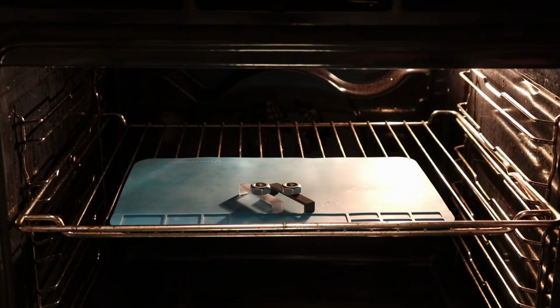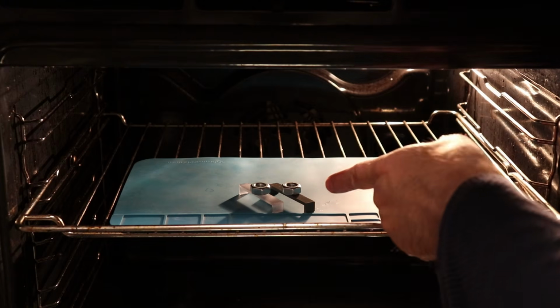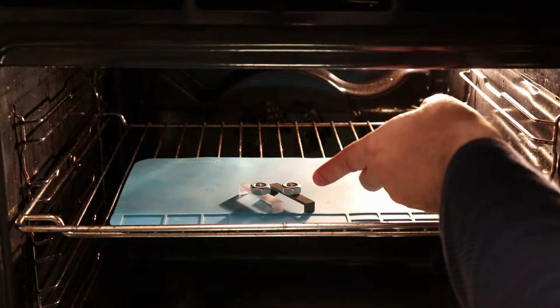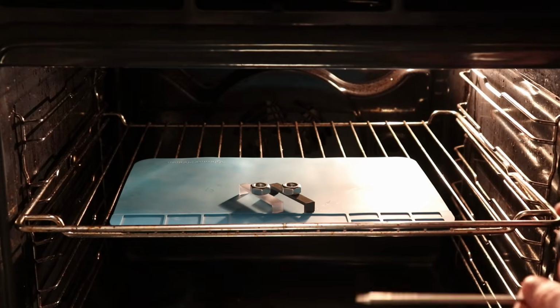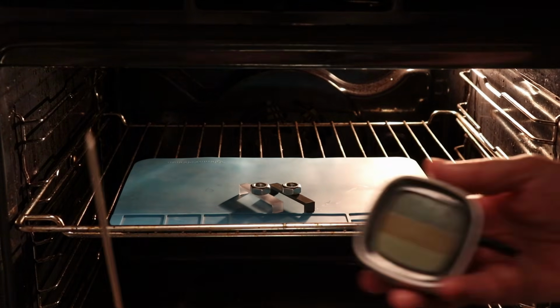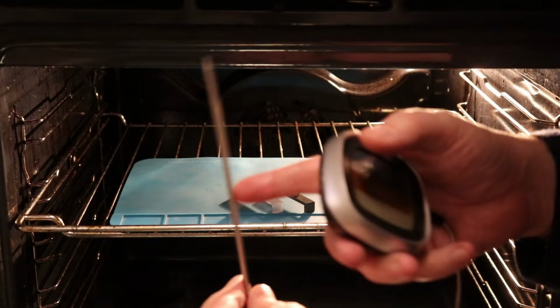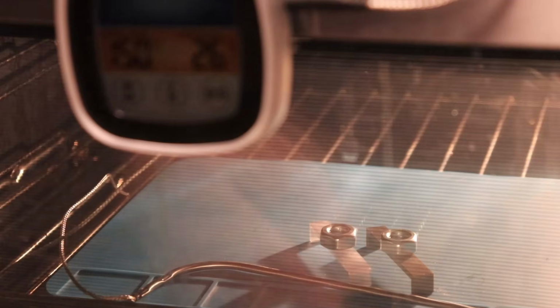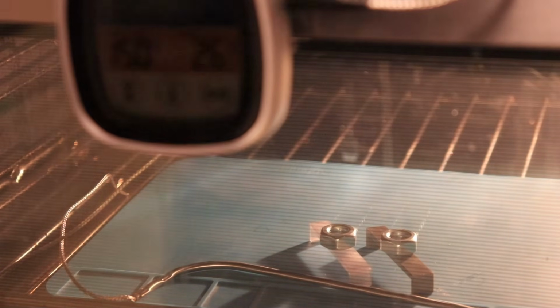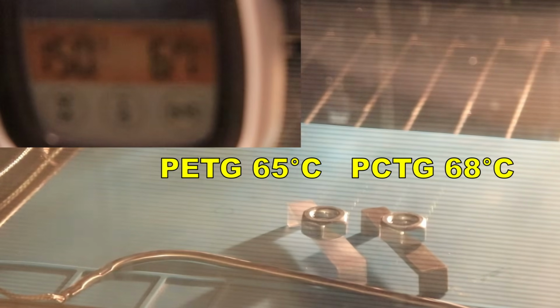And it's time for the temperature test, and according to specifications, I'm expecting that PCTG will perform better in this experiment. And I will follow the temperature with this thermometer, and this is the sensor for it. I want to record the temperature when it reaches approximately 0.5 mm deformation. This is a time lapse of approximately 4 minutes, and I will analyze this frame by frame to get the temperatures of the deformation.